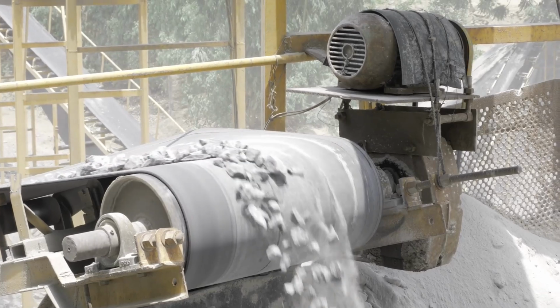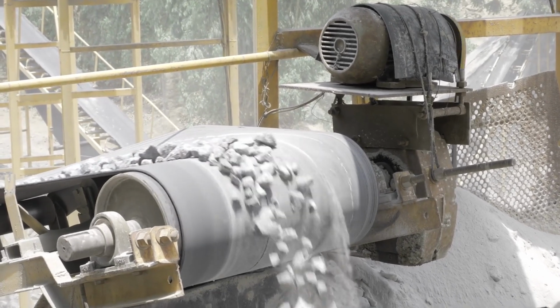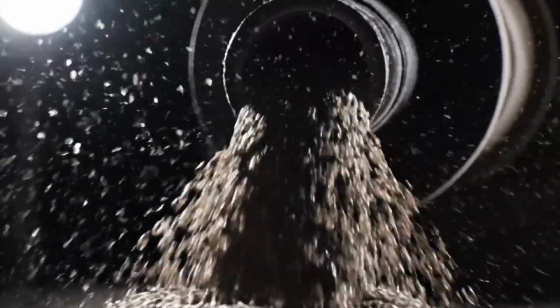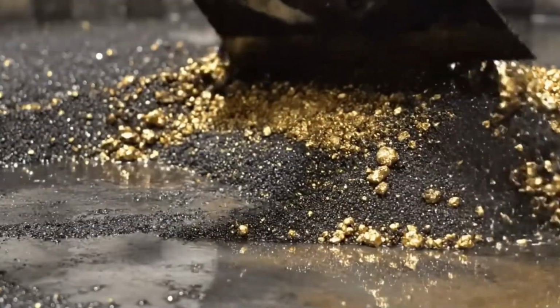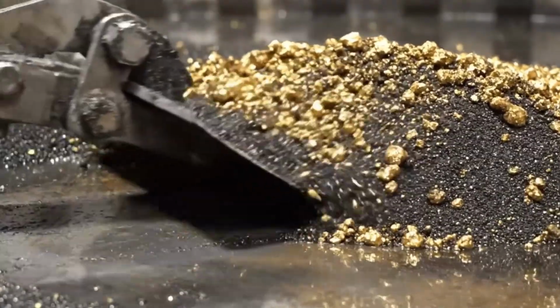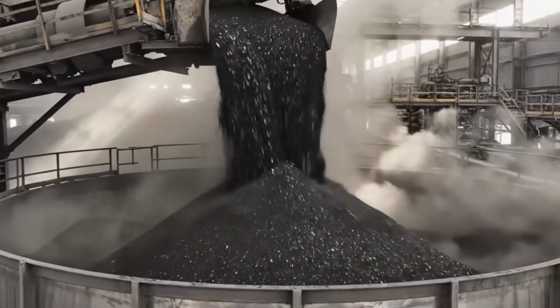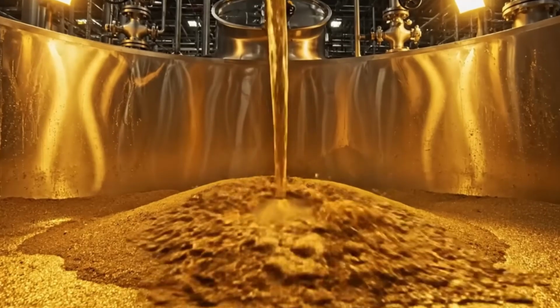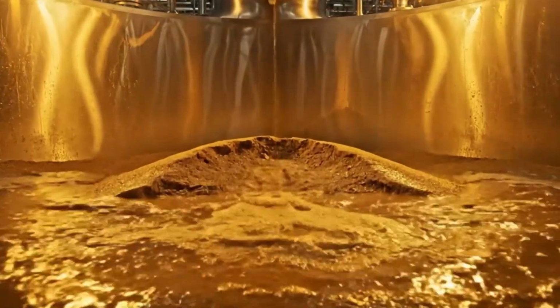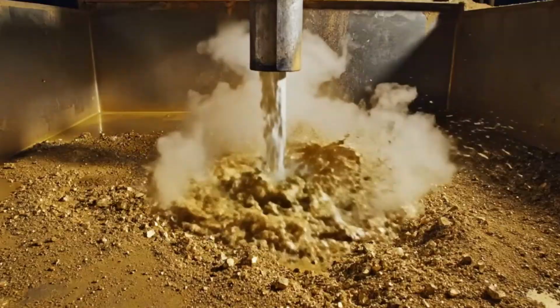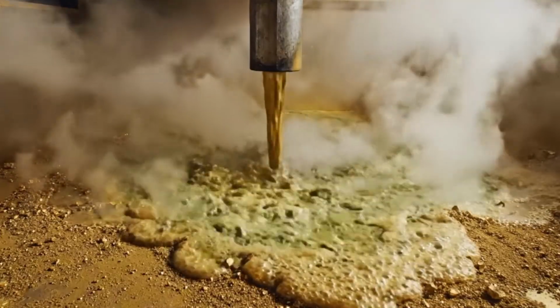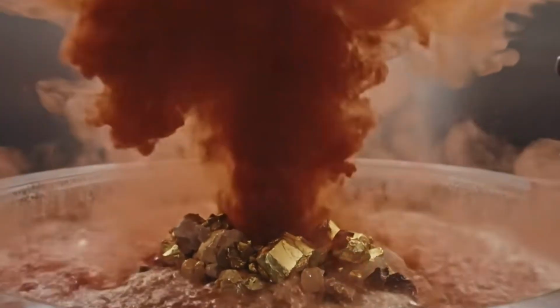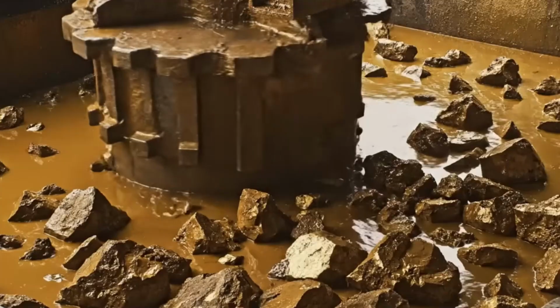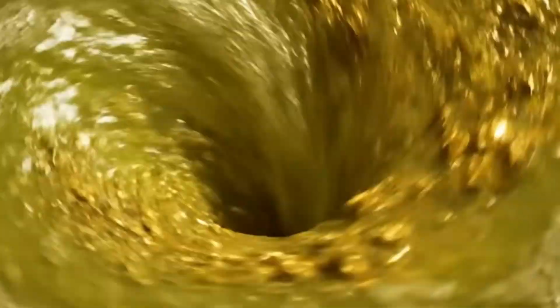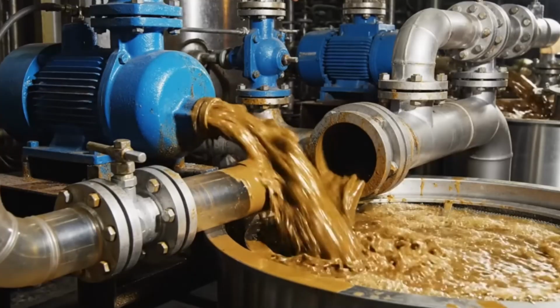Once the ore has been ground into slurry, it moves into the leaching stage, where chemistry takes over from raw force. The slurry gets pumped into a bank of large tanks, and a weak cyanide solution is mixed in thoroughly. Cyanide bonds extremely strongly with gold at the molecular level, pulling gold particles out of the surrounding rock and dissolving them into the liquid. This technique, cyanide leaching, dates back to the 1880s and remains the dominant gold extraction method worldwide because it works so well even on ore with very low gold content. The tanks keep the slurry constantly stirred for 24 to 48 hours to squeeze out as much gold as possible.